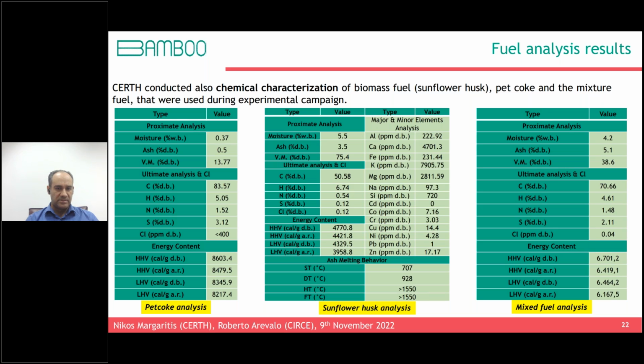So here we see the main results: petcoke analysis, sunflower husk analysis, and mixed fuel analysis in terms of moisture, ash, volatiles, chlorine, hydrogen, nitrogen, sulfur in the fuel, and also energy content of the fuel. So we see here the high energy content of the petcoke, around 8,000, and half of this, around 5,000, is the heating value of sunflower. So the mixed fuel, the mixture of these fuels, has a heating value of around 6,700 kilocalories per kilogram energy content.